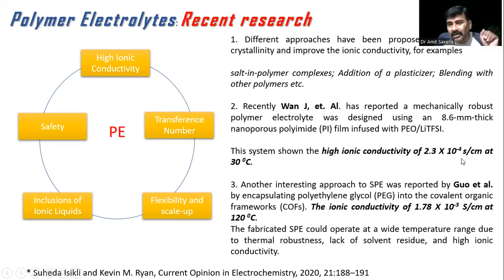and the best ionic conductivity offered to date is with PEO in particular. It's of the order of 10 to the power minus 4 Siemens per centimeter. But when we increase the temperature, we can get up to minus 2. Also, in our case, we get a conductivity of the order of minus 2 when we increase the temperature beyond 65 degrees, below the melting point of PEO.